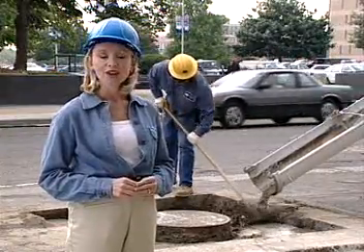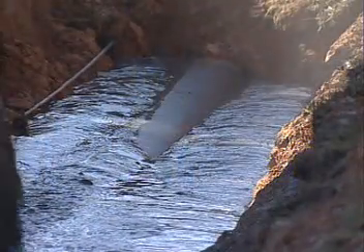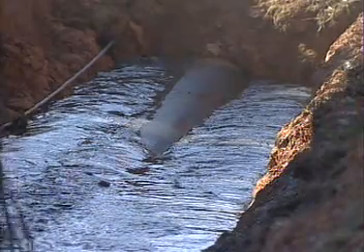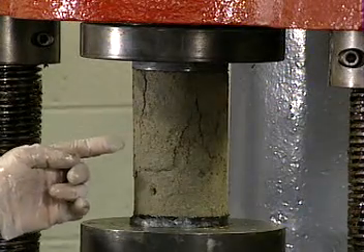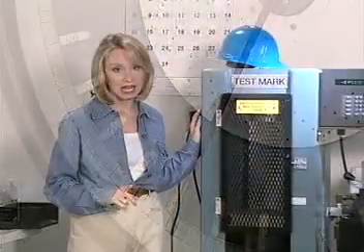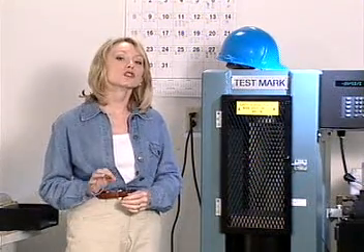Flowable Fill is typically designed to be self-leveling and self-compacting with an unconfined compressive strength between 30 and 150 pounds per square inch. The compressive strength of Flowable Fill is measured in accordance to the same standards as concrete. However, the testing equipment utilized must be able to accurately measure strengths as low as 30 pounds per square inch. The American Standards for Testing Materials has approved 2 other test methods for strength or bearing capacity, which have proven to provide more precise and accurate results.